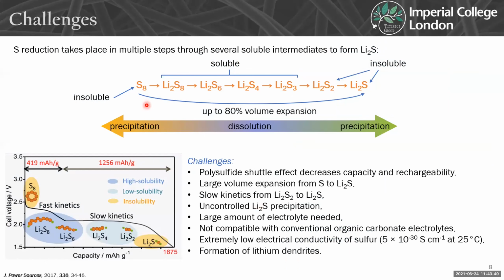The reduction of sulfur, as I mentioned earlier, is not just a straightforward conversion between sulfur and lithium sulfide, but it goes through a series of intermediates that we call the polysulfides. And these intermediates are all soluble. So the conversion reaction actually takes place not in the cathode, but in the electrolyte solution. There are several challenges associated with this conversion reaction. When you convert from sulfur to lithium sulfide, you have a really large volume expansion, so we need an electrode system that can accommodate that volume change. Again, because we have the dissolution of these polysulfide species in the electrolyte solution, they can shuttle, what we call shuttling, across the battery.